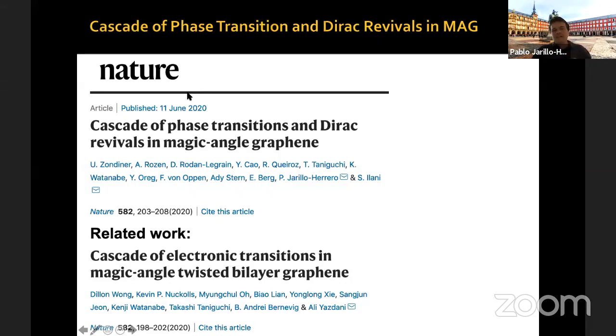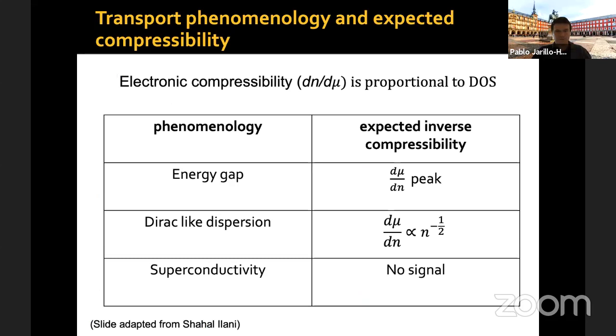We showed that there is a cascade of phase transitions which happen as you go through the integer fillings, 1, 2, 3, 4 electrons per moiré unit cell in this system, okay? And these were the first thermodynamic measurements of magic angle graphene. So not only transport, there were quite a few transport experiments, but this was the first local thermodynamic measurement; there was an earlier paper by my colleague Ray Ashoori about it, but the first local thermodynamic measurements of magic angle graphene. So I want to tell you about electronic compressibility.